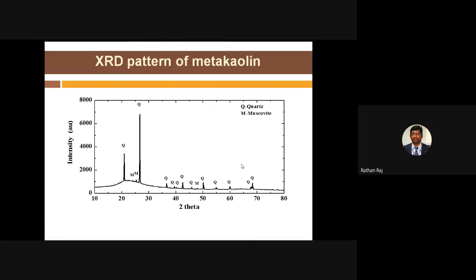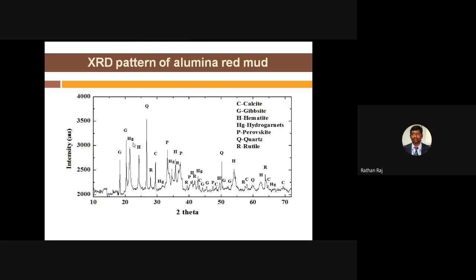And in the XRD of red mud, many chemical compounds or elements are identified. Some of them are calcite, gibbsite, hematite, hydrogarnet, perovskite, quartz, and rutile. See, the unwanted and undesirable material called rutile is identified in this material. This rutile is nothing but titanium oxide.